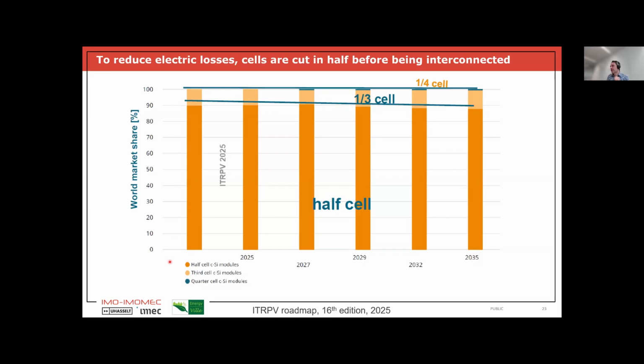if you put it into a PV module. And so actually to reduce resistive losses, typically before the cells are interconnected and put into the module, they are cut in two. So you see here, most PV modules that are made are based on half cells. And some are even based on cells where it's only 1/3 of the size. The main reason for doing that is if you reduce the area of the cell by 2, you also reduce the current that it produces by 2, and you have much less resistive losses. And this gives you a little bit extra power.